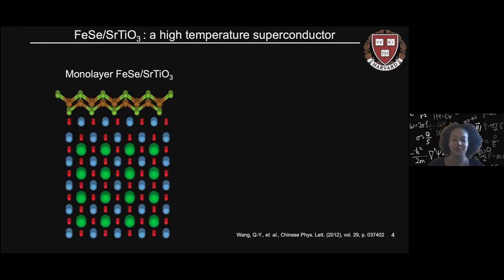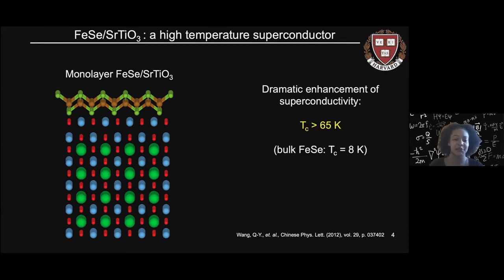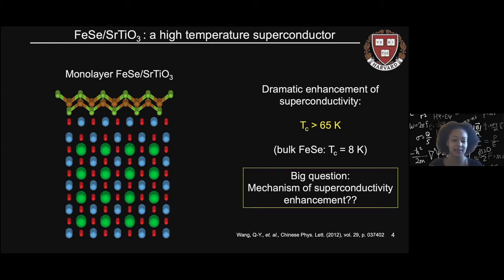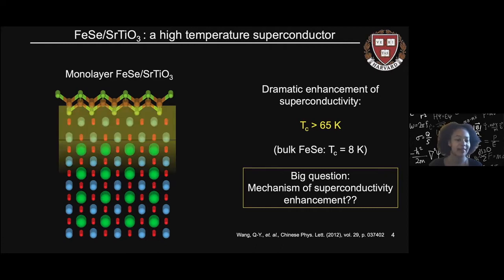So I'll begin with a brief introduction to the material. Monolayer iron selenide on strontium titanate is a high temperature superconductor, which has sparked great interest in recent years due to its dramatically enhanced transition temperature of greater than 65 Kelvin. This is dramatically enhanced compared to the bulk iron selenide, which has a transition temperature around 8 Kelvin. The big question motivating research of this material has been, what is the mechanism of superconductivity enhancement? Specifically, what could be important at the interface of this material?